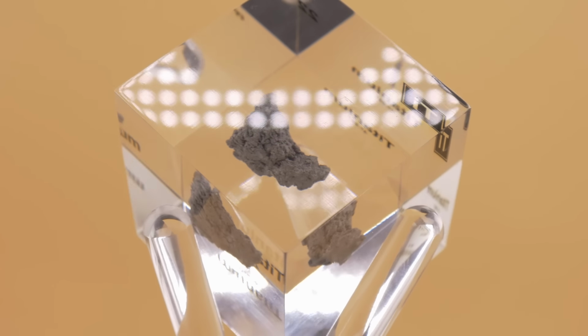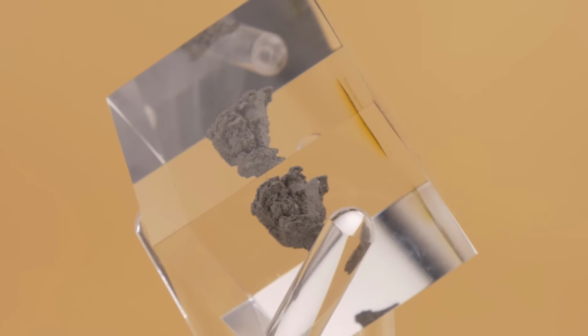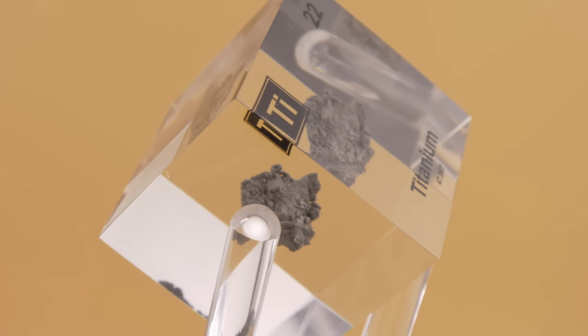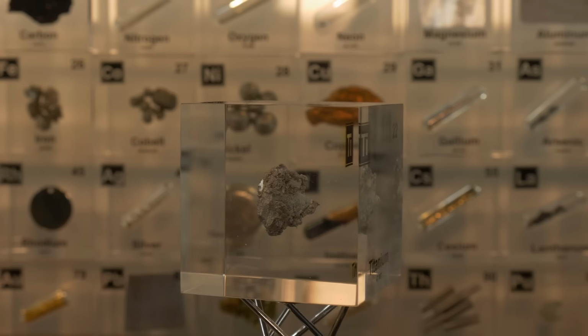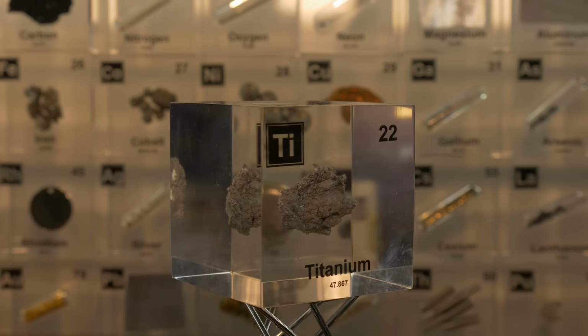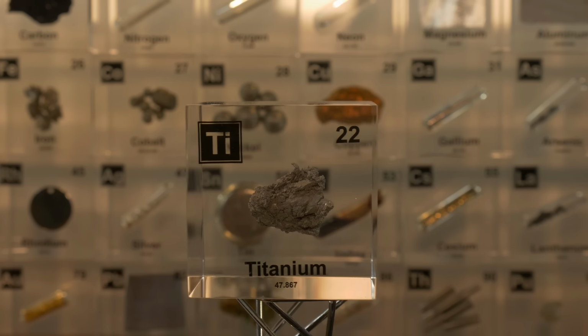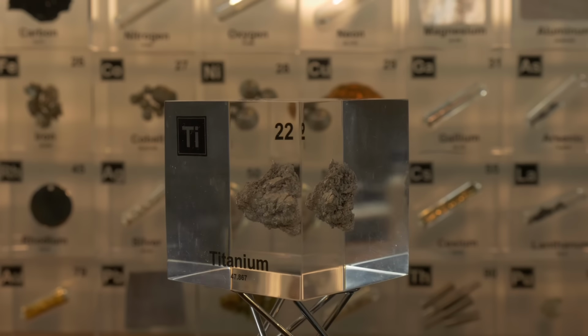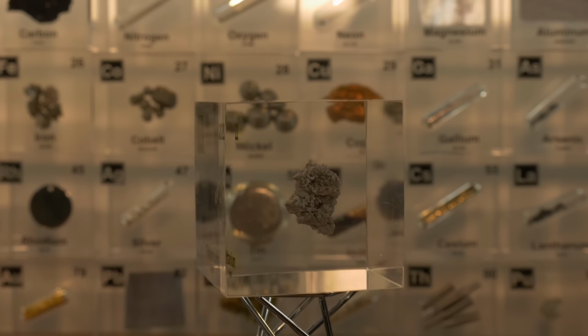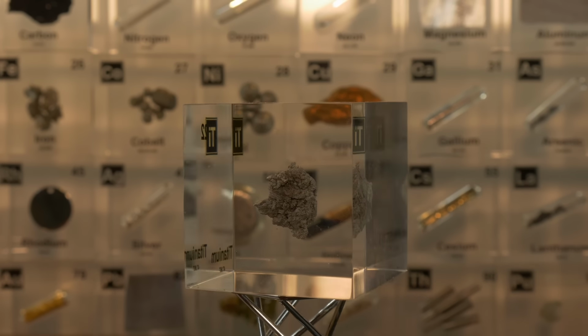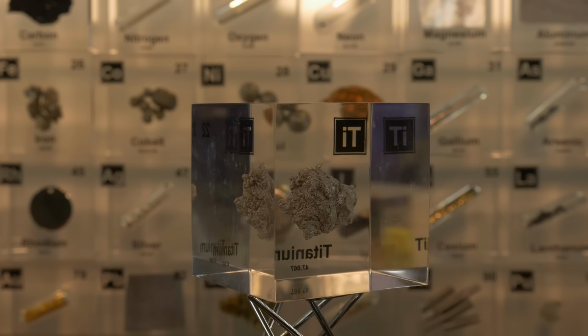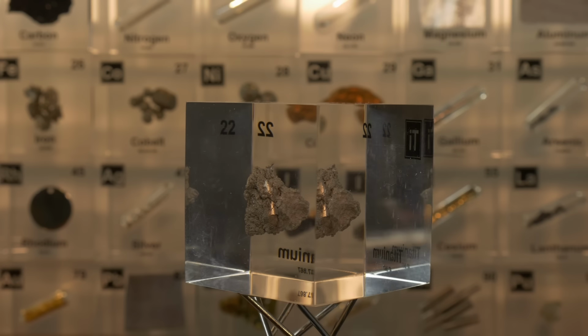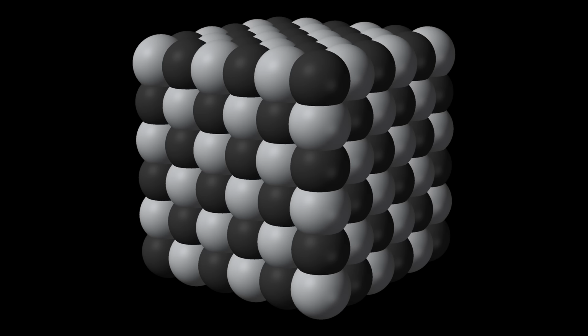Getting titanium from its ore is not easy. It's one of the more complex metal extraction processes. Why? Because as we learned, titanium just loves oxygen. Its ores are oxides like titanium dioxide or iron titanium trioxide, and it holds that oxygen tightly. We can't simply throw it in a hot furnace with carbon the way we do with iron ore in a blast furnace, because titanium would rather bond with the carbon than let go of the oxygen, yielding titanium carbide, which would be brittle and useless.